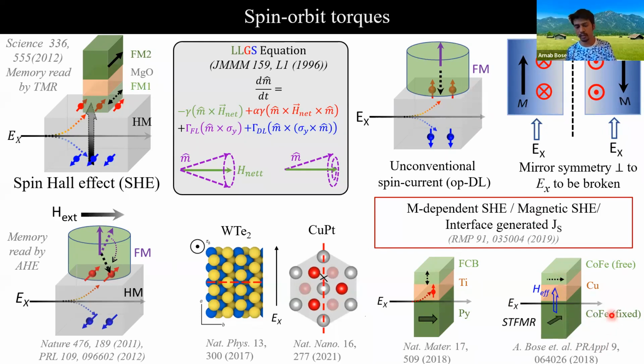In this case, however, we tried to pin the magnet or pin the spin source. Still, it can be susceptible to external magnetic field perturbation. So ideally, we will need a spin source which is very robust, such as platinum, but at the same time, we need the magnetic ordering. This can be simultaneously fulfilled if we have an antiferromagnet, which we'll see in the later part of this talk.